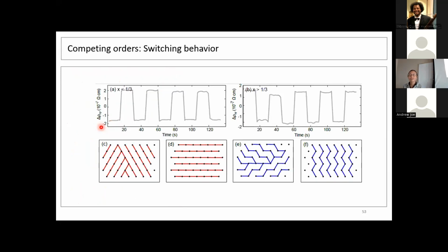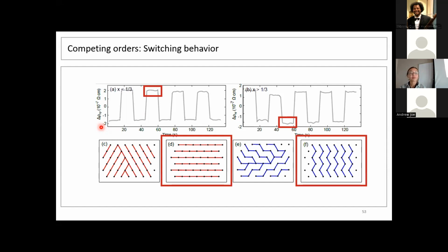So now we have a pretty good idea of what's going on microscopically when we're switching our material. It's not the Néel vector that's reorienting, but it's actually the directions of these domains. So that's why when we have the same pulse bringing our iron deficient sample to a high resistance state and our iron excess sample to a low resistance state, it's because we're preferring these two orientations of domains, but they're fundamentally different domains to start off with. They're different kinds of order.